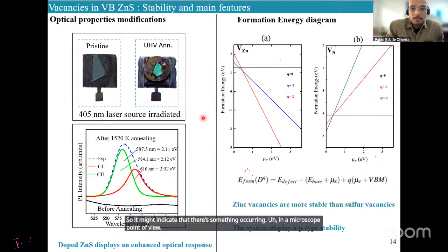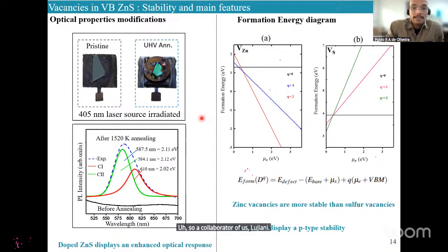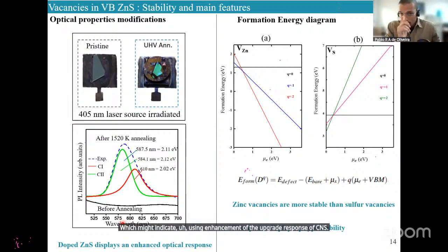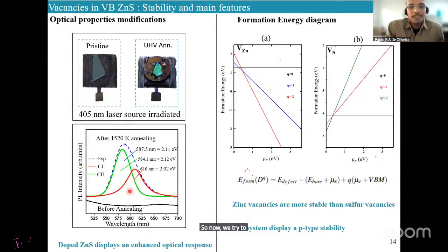So it might indicate that there's something occurring from a microscopic point of view. A collaborator of ours, Luciani, carried out some luminescence experiments and revealed that before annealing there was no emission, there's no luminescence spectra. However, after the annealing process at the temperature mentioned here, we obtained two components. These components fall exactly in the visible range, which might indicate a huge enhancement of the optical response of ZnS. So now we try to model what is going on behind this experimental finding.